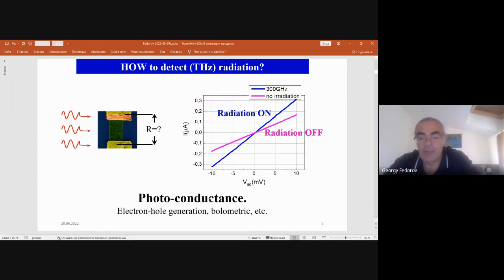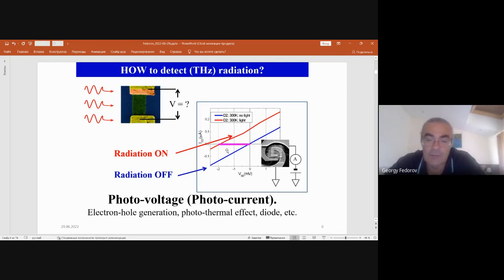The reason for that may be that you create electron-hole pairs like in semiconductors, or you just heat this system, which is called the bolometric effect, and so on and so forth. There can also be another very different effect, which is that your IV curve doesn't really change the slope much, but it shifts with respect to its original position, and there is a certain built-up voltage corresponding to zero current. So this is photovoltage. It's more or less similar to what we get in solar batteries, but on a much smaller voltage scale. This type of detection is in many cases preferential because you don't have to bias your device, you have smaller noise, and you have less power consumption to operate it.